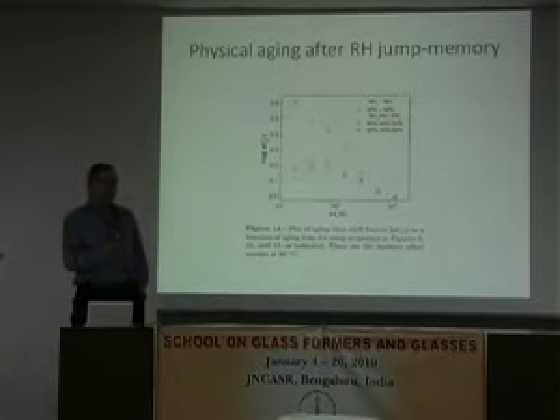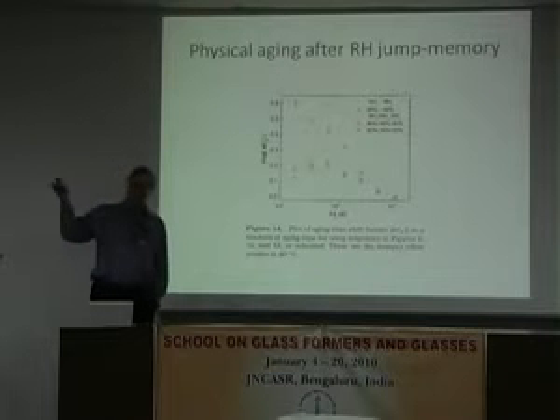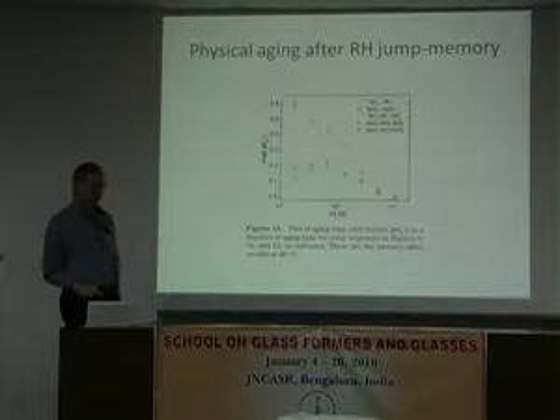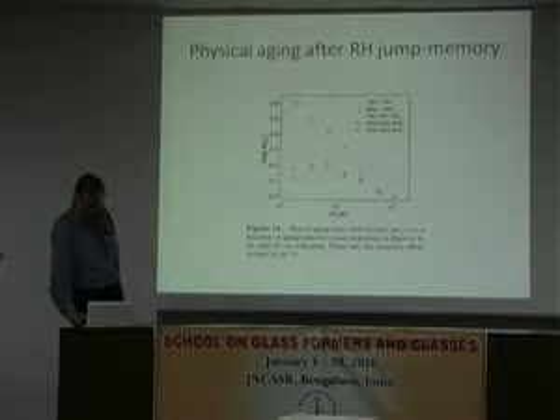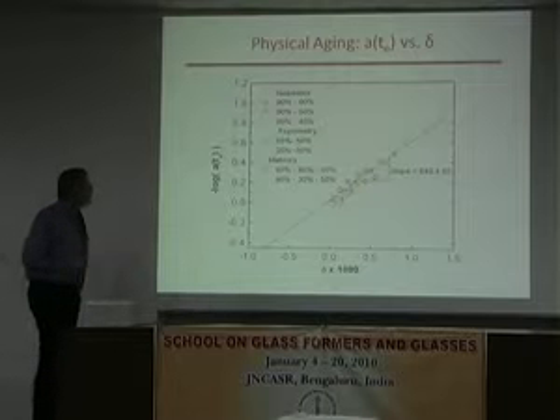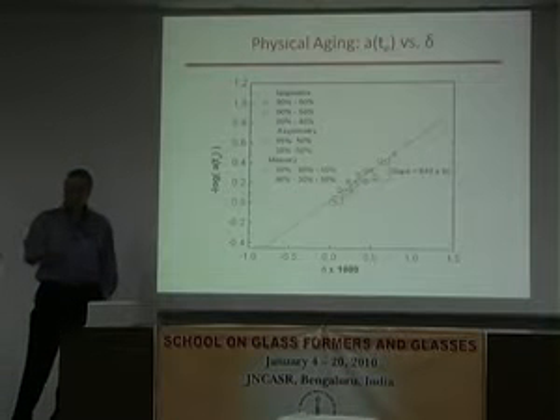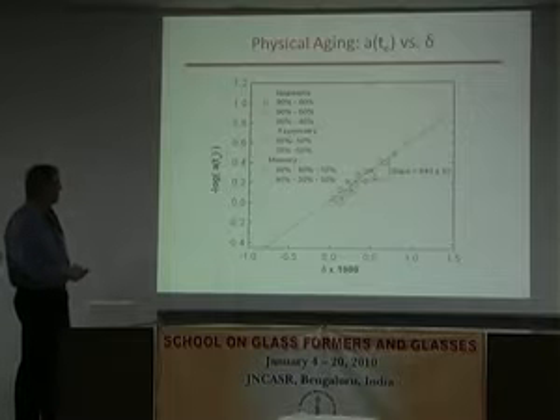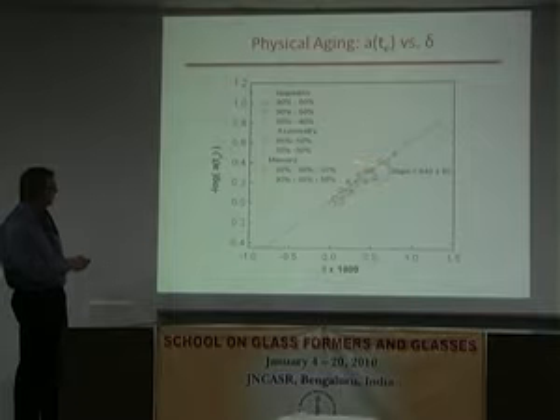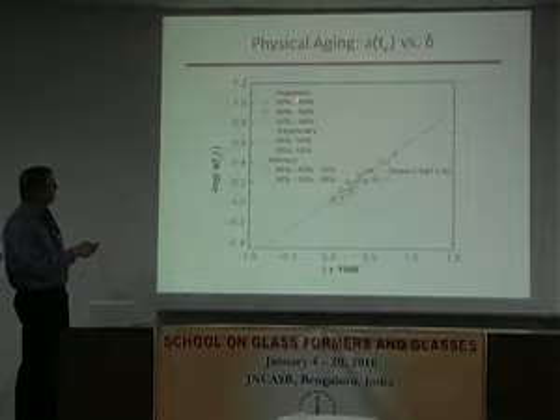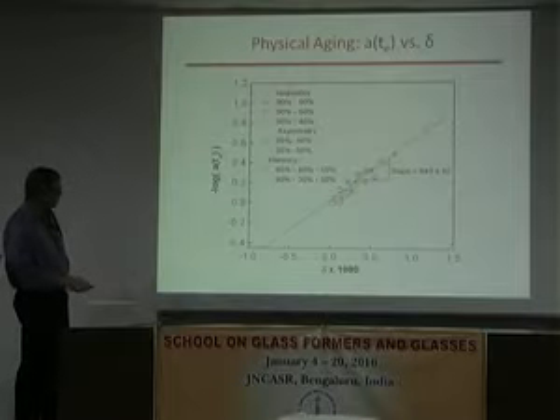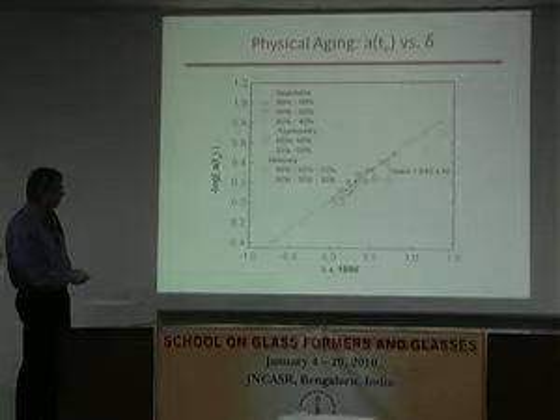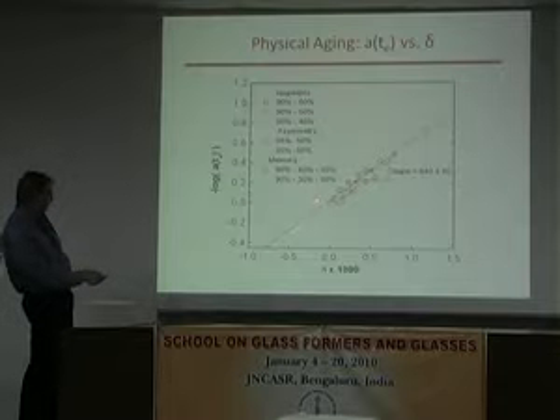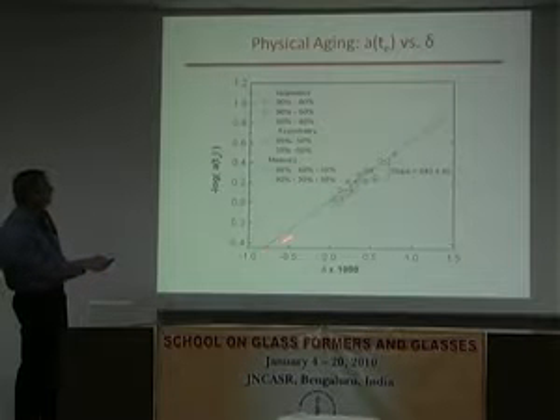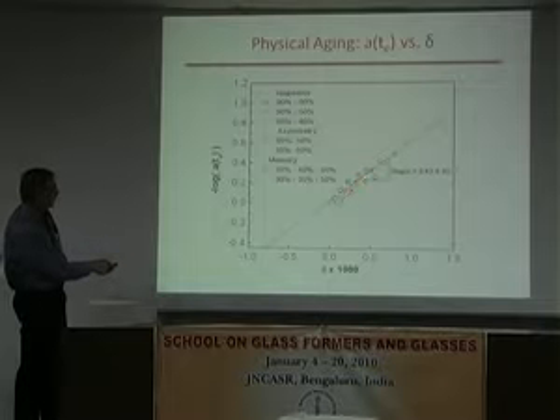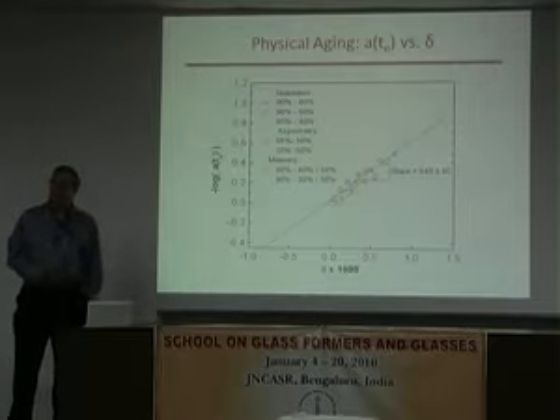So of course we don't think of it that way, but it's the time and then the aging time that are the two times that Sri's talking about, right? And then this just shows, just like Struik found with his volume measurements after temperature jumps, we find that after these different memory, asymmetry, and isopiestic histories, as a function of the volume departure from equilibrium in this case, we find everything falls, oops, there's some points down here too. I guess you probably can't see them. But we get everything falling pretty much on a single line.